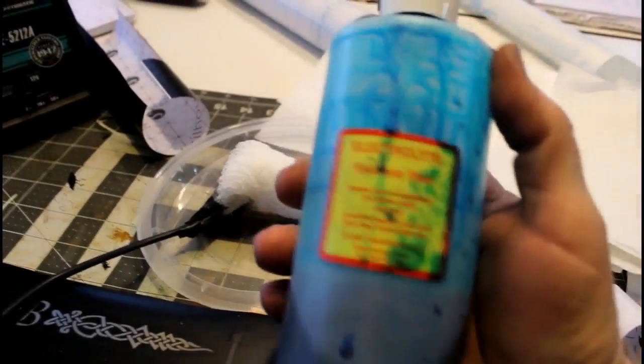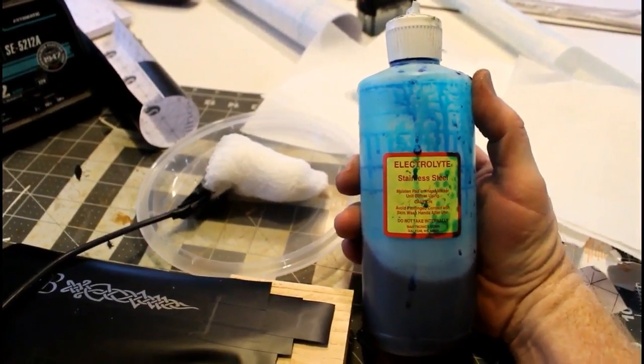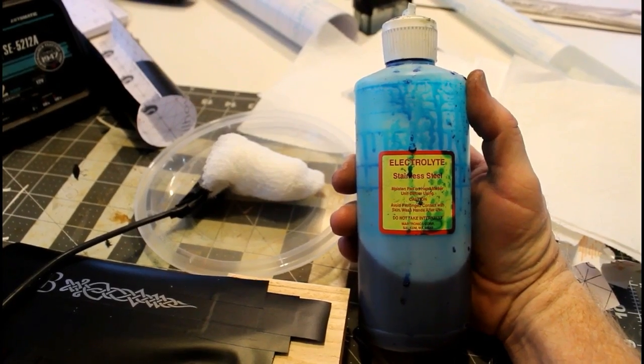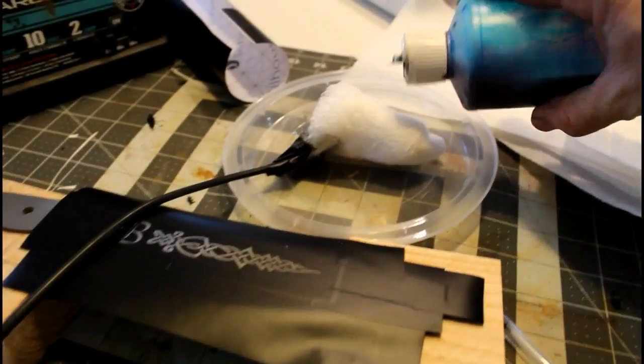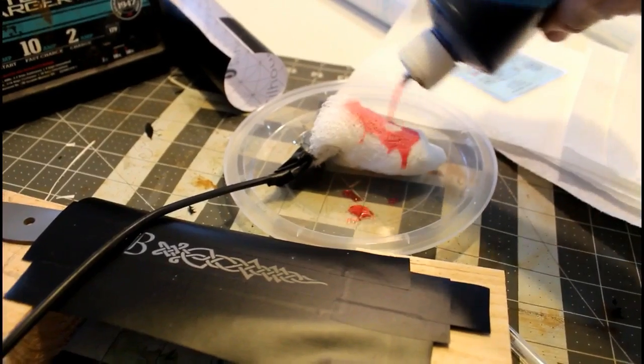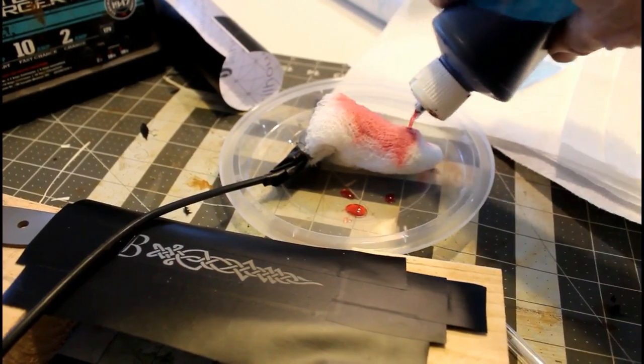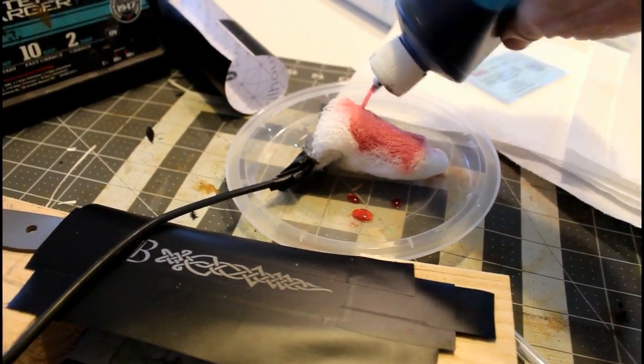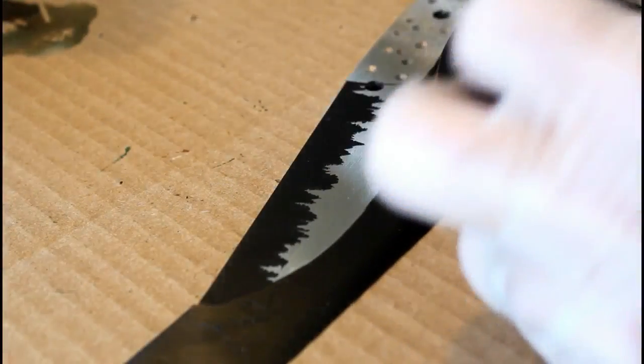For stainless steel, in the past I've always etched with a saltwater electrolyte. It doesn't work very well on stainless steel. So for stainless, I highly recommend going out, and for a few bucks on eBay, you can buy a stainless steel electrolyte solution, which works much, much better.